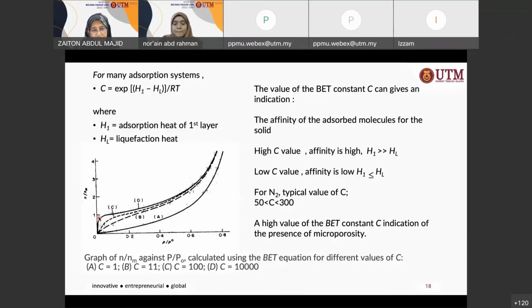If you compare the D isotherm and the A isotherm, this indicates the presence of micropores, because you have a very high intake at very low pressure, and you also have a knee here. Right? So basically, this might be a type 1 plus a type 4. If you can see the hysteresis loop, then it might be a type 1 plus type 4, or maybe a type 2.